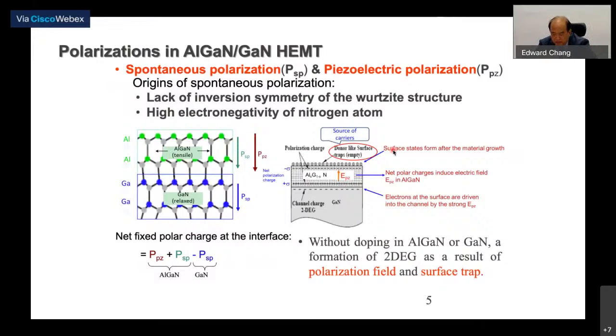So from here, you can see that in the two materials, because of piezoelectric and spontaneous polarization, that generates a high electric field within the structure itself. And then on the surface, there are a lot of donor states, which give the electrons. So in this way, you generate a lot of electrons from the surface states, and then due to the polarization electric field, these electrons are driven to the 2DEG channel. That's why you have high current and also high breakdown voltage for the material.